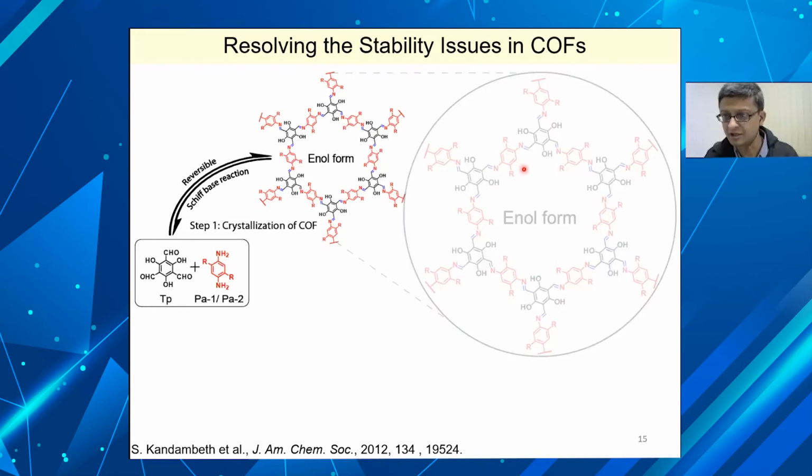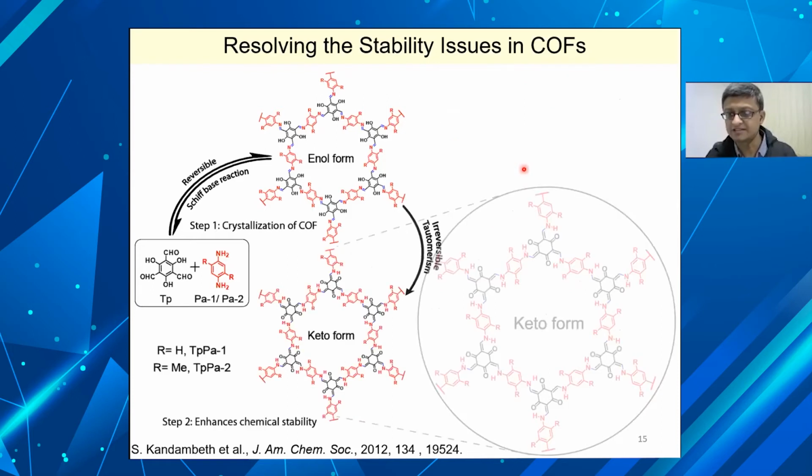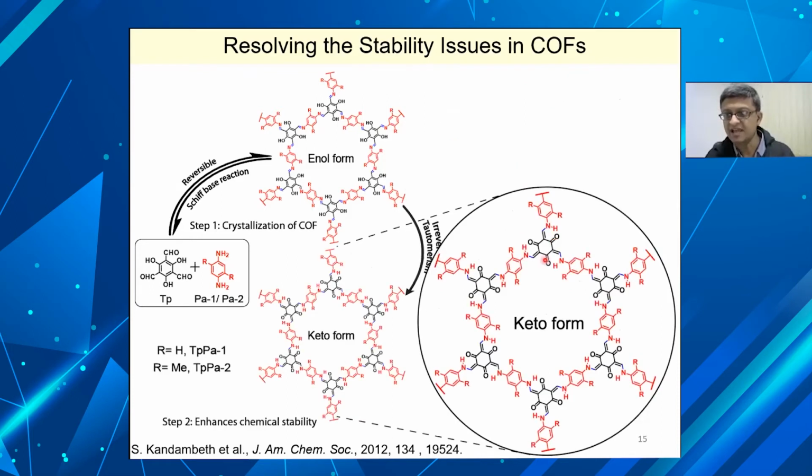Now because of the tautomerization, you get this nice tautomeric structure, where it loses the aromaticity. Here you can see C double bond O, C double bond C, C single bond N, C single bond C. None of these are hydrolyzable in base and acid. Of course, if you add aqua regia or very concentrated sulfuric acid, these will go bad. But beyond that, hydrochloric acid and sodium hydroxide should be okay.